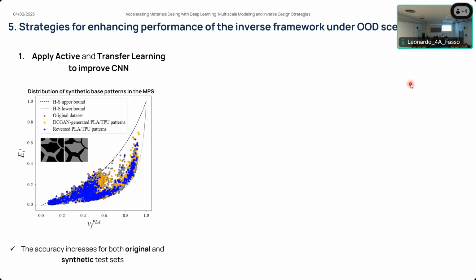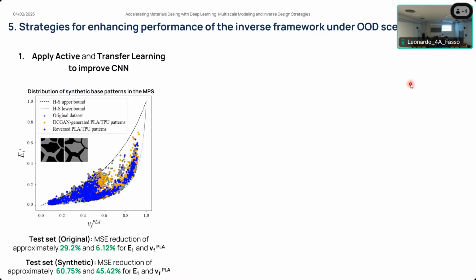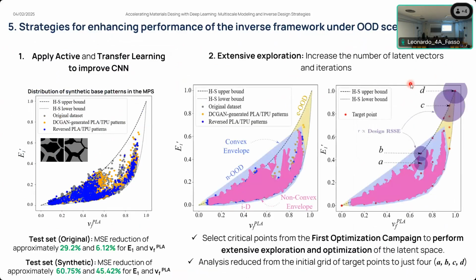We introduce a small fraction, around 20% of new synthetic samples, in the original training dataset, retrain the convolutional neural network, and with this we can observe an important decrease of the error, interestingly, both for original samples and for synthetic samples. So this is a very effective strategy to improve the predictor module, which is one of the components of the entire framework. The other component of the framework is related to the optimization of the latent vector.